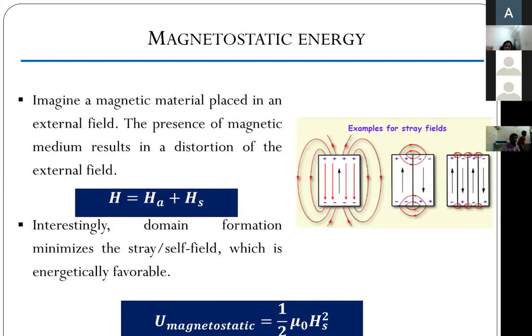Then the next is the magnetostatic energy. Let's say you have this applied field, and we place a magnetic material in the external field. Then the total field surrounding the magnetic material does not remain equal to the applied field, because the presence of the magnetic medium changes the field around. So the total field, when we try to measure it, will be the sum of the applied or external field plus the self field. This is also called the demagnetizing field, the self field that is created by the magnetic material in response to the applied field. It can also be seen as a distortion.